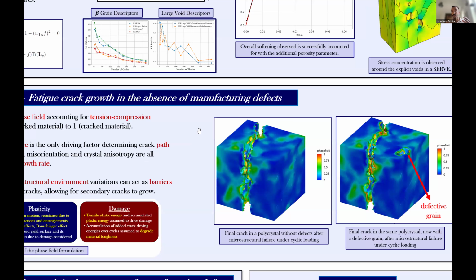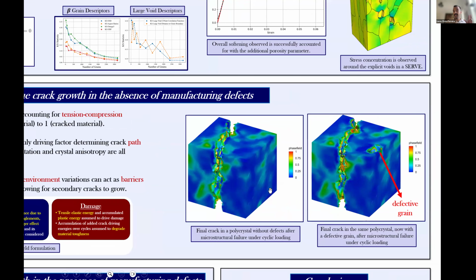So depending on the microstructure, a certain crack tip might branch out, might be arrested, might propagate in certain directions. And we were able to see that for the same volume, if we have on this path a microstructure that drives the crack growth, but if we add a defect in a region that doesn't have a microstructure prone to crack growth, the crack is not necessarily going to go through there. It's going to go through the microstructure where the energies and the formulation allow it to grow faster. But this is when we apply a defect at a subgrain level.